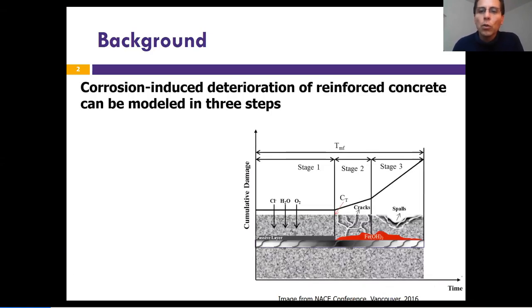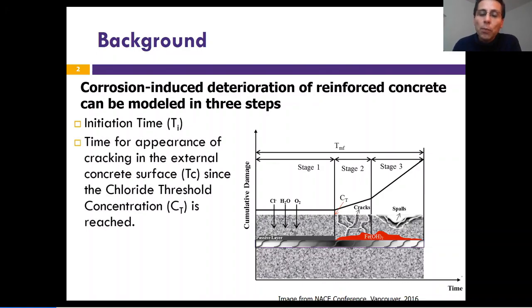So the background: I'm going to describe a little bit what corrosion means in reinforced structures. You see a diagram that illustrates how the rebar embedded in the concrete is going to corrode with time. You see the time on the x-axis, cumulative damage on the y-axis. We call it, in corrosion, three stages of damage in the reinforced structures. When you expose the rebar, there is a stage one where all the precursors of corrosion, all the environment, penetrates, and there is a time when you start to activate that rebar because the precursors penetrate the passive layer that is formed naturally due to the alkaline environment, and start to crack and induce damage.